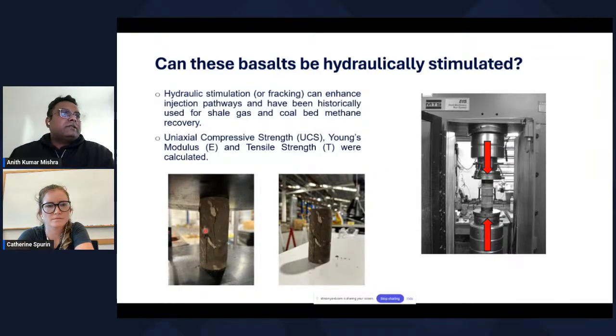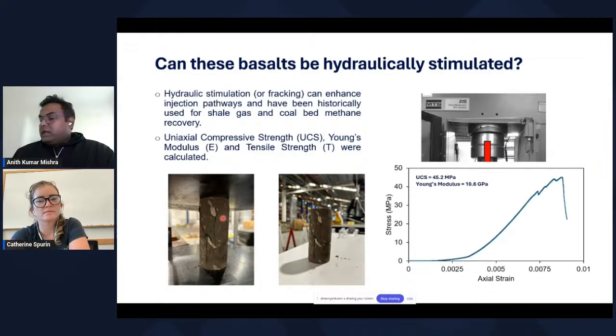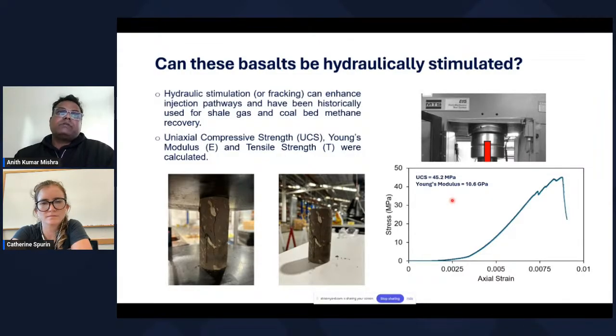And with this test, what we found is that the fracture networks in the basalt have some preferential direction of fracture propagation. For example, if you look closely at this sample, you can see the fractures actually initiated along the interface between the secondary minerals and the primary basalt. We can also mechanically compute the different geomechanical parameters, because these parameters are needed to understand whether we can hydraulically stimulate the basalts and whether it is safe to do so, because it can sometimes trigger seismic activity, or sometimes collapse in the subsurface as well. So these are the parameters that we are deducing right now.